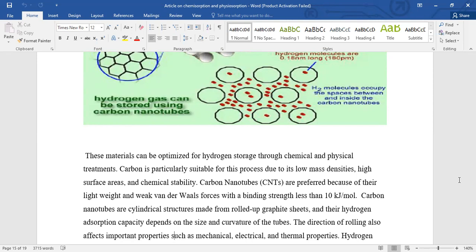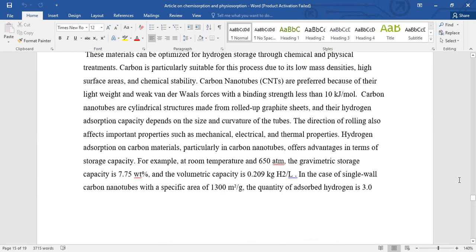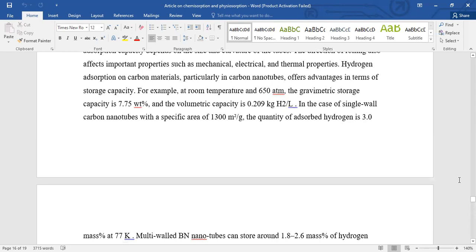Carbon nanotubes are preferred because of their light weight and weak van der Waals forces with a binding strength less than 10 kJ per mole. Carbon nanotubes are cylindrical structures made from rolled up graphite sheets, and their hydrogen adsorption capacity depends on the size and curvature of the tubes. The direction of rolling also affects important properties such as mechanical, electrical, and thermal properties. Hydrogen adsorption on carbon materials, particularly in carbon nanotubes, offers advantages in terms of storage capacity. For example, at room temperature and 650 atm pressure, the gravimetric storage capacity is 7.75% weight, and the volumetric capacity is 0.209 kilograms hydrogen per liter.